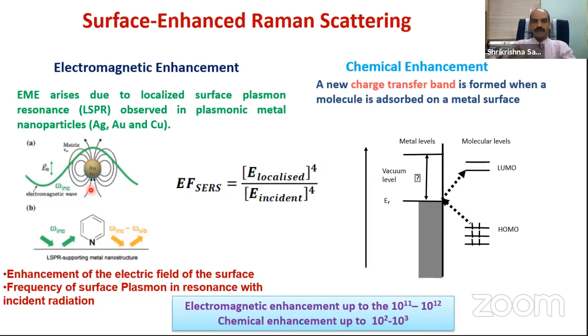At that time people were not aware why it is happening, but now we know that if you can make a nanostructured surface of these metals, then you will have this surface plasmon resonance, and in that case these plasmons will oscillate with a certain frequency, and if that frequency is matching or close to the incident radiation, then there will be an enhancement in the electric field. Now the electric field will be enhanced in two ways. The first electric field is associated with the electromagnetic wave. That electric field will be enhanced because of this plasmon resonance, and this electric field enhancement will cause the change in dipole moment, and that will give you the enhanced intensity.